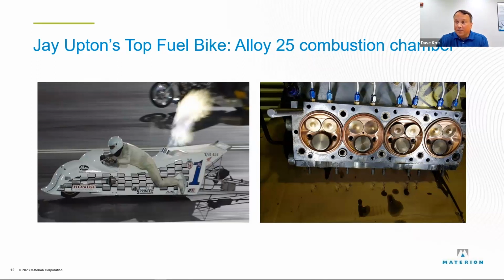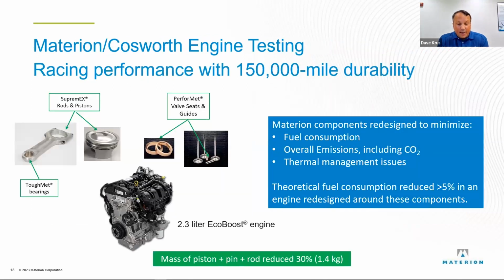So moving on to the other two materials, right? In the last webinar, last September, we talked about some engine testing that we did with Cosworth in the UK. There was a 2.3 liter EcoBoost crate engine that we took and had them redesign specifically the piston, the pin, and the rod to minimize the amount of mass. As you can see in the green box, they took out 30% of the mass, 1.4 kilograms, by reducing the piston weight by 20%, just making it thinner in places where the aluminum had to be more bulky. And by replacing a steel rod with an aluminum rod, they took 40% of the rod mass out of it.